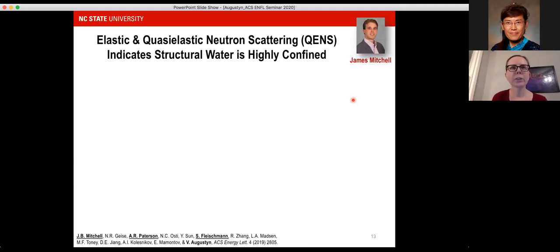Again, these materials are kind of hybrids, right? They contain an inorganic phase, the tungsten oxide, but then they also contain water. So the techniques that are really useful for these materials include things that are more often found in the polymer field. That includes things like elastic and quasi-elastic neutron scattering. We did these experiments at Oak Ridge National Laboratory with our collaborators, Eugene Mamontov and Naresh Osti.